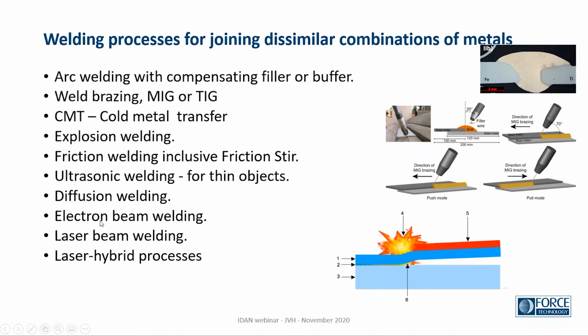Electron beam welding, where we have an electron beam as a heat source, was popular for very deep, very narrow welds previously, but as it has to be performed in vacuum, you can only weld a certain size of items, and you need to do it like a batch to get vacuum and to get to normal pressure for each batch. So the area where electron beam welding was used is, for the most part, solved by laser beam welding today. Having more power, we can almost do the same as in electron beam welding.